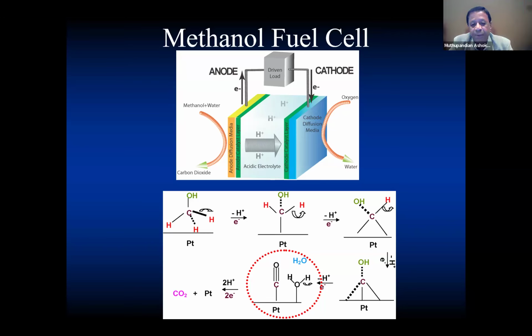Okay, so what happens is the methanol gets oxidized. During that process, carbon monoxide is produced as an intermediate product, and carbon monoxide has a very strong affinity to platinum. And so carbon monoxide will not leave the platinum surface, poisoning the catalyst or the electrode. So the whole process comes to a standstill. So basically the electrode gets poisoned.